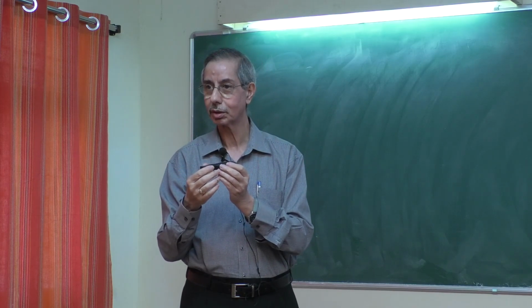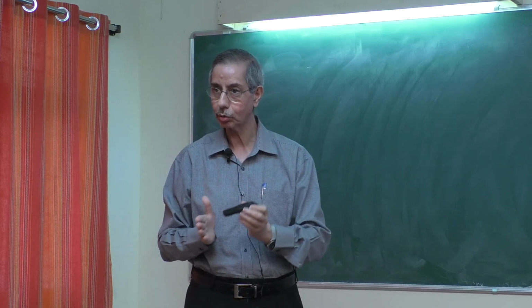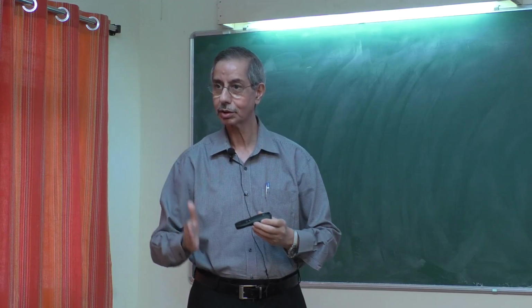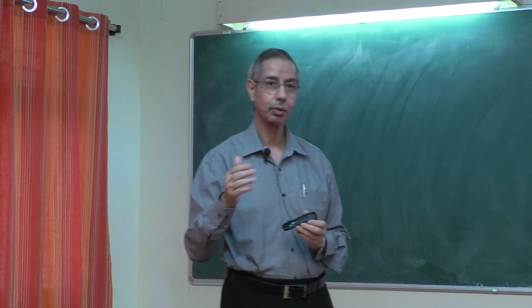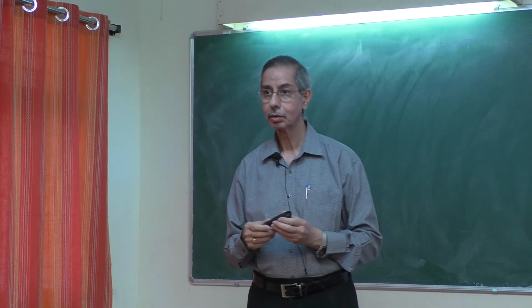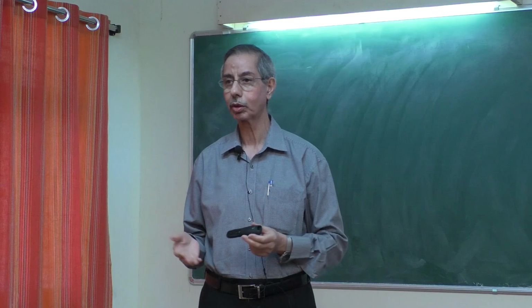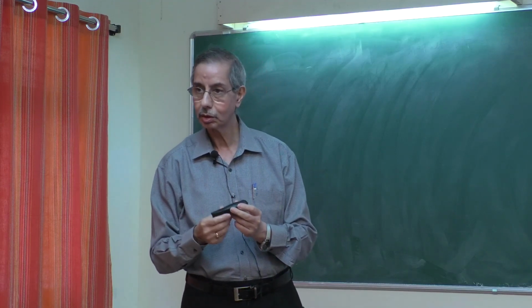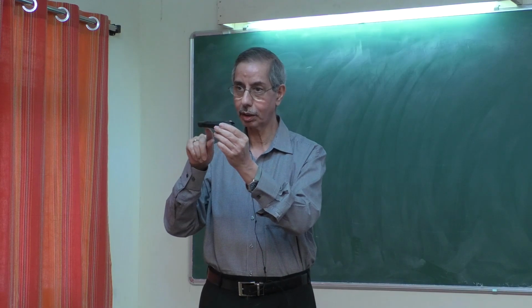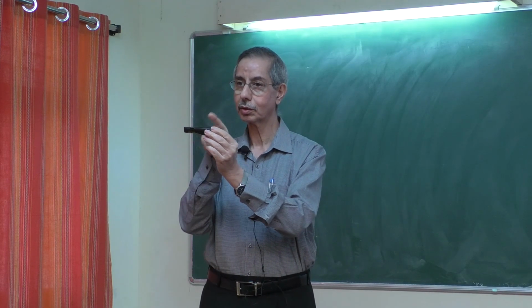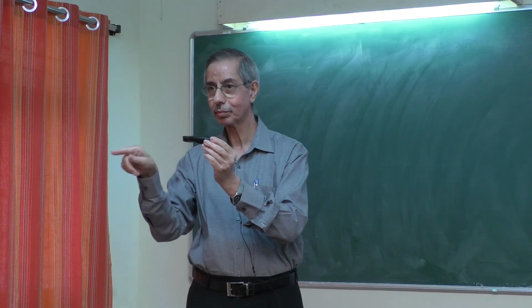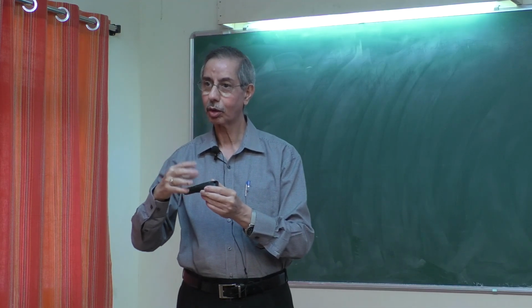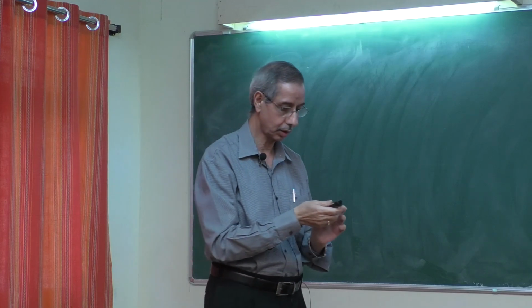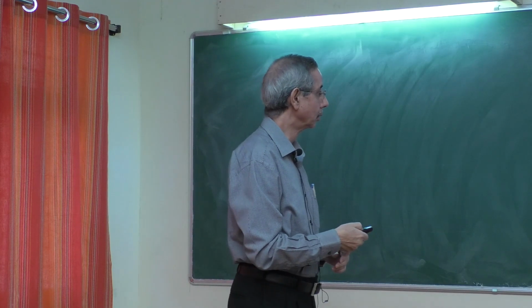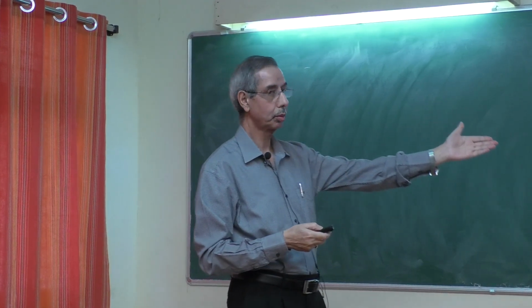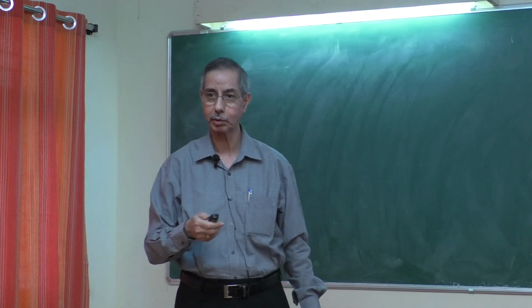So this you are able to see when you apply the field, but it is already there because we already have magnetic dipoles inside. Dipole interactions will try to orient dipoles in some direction, right? So that's why this magnetostatic interaction is basically a dipole-dipole interaction in the absence of any external field. For example, if you have a system like this and there are dipoles, dipoles will also try to orient in some direction, which will be some easy direction according to the magnetic dipole interaction. So let us see now, that would be more clear. The equilibrium state of the system is when this total energy is minimized.